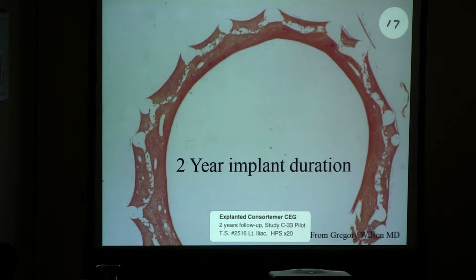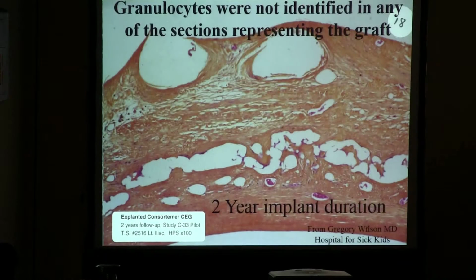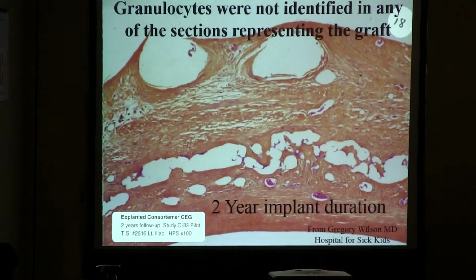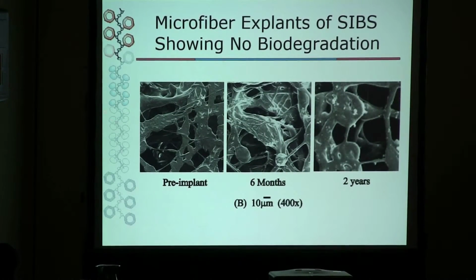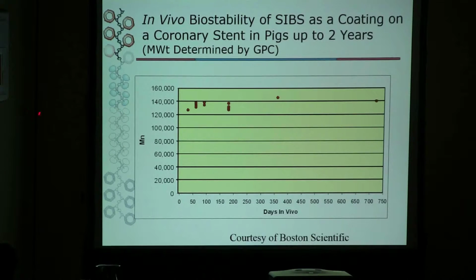So we looked at it over 2 years as stent grafts, and we found that there were no sections identified that showed any granulocytes. And it was a very benign reaction, very different than anything we've ever looked at or that the pathologist at Sick Kids ever looked at. We also looked at little fibers, and after 2 years, we saw no cracking. And if you want to measure molecular weight change, you just plot, if you have a decrease in molecular weight, it means your polymer is degrading. But we showed over 2 years in contact with metals that there's no decrease in molecular weight. So it's a very stable polymer, as expected.